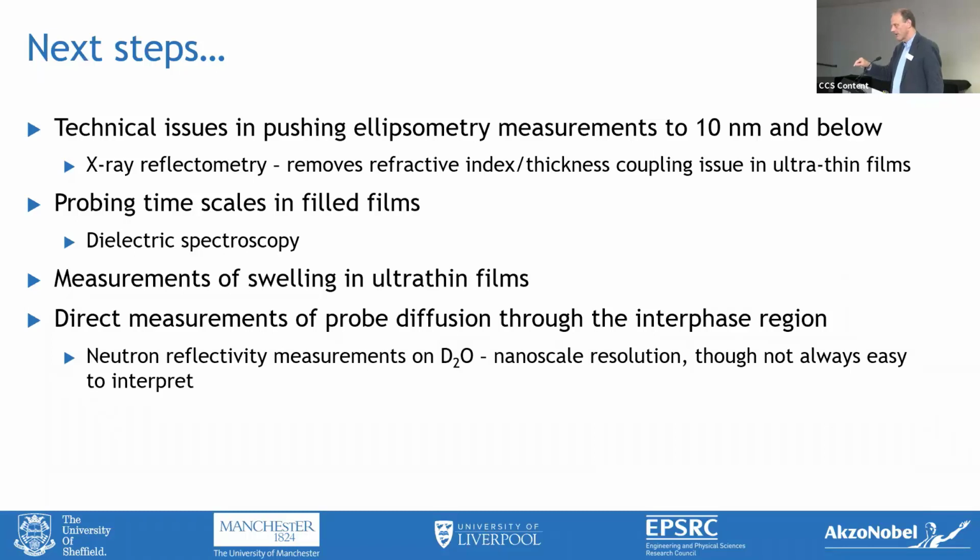It's just that the temperature dependence is less. As a first approximation, I would assume that as you reduce the temperature at high temperatures, you'll see an Arrhenius, exponential temperature dependence. As you go through the glass transition in the bulk, that Arrhenius dependence turns over into a Vogel-Fulcher temperature dependence, which is much, much stronger, really super exponential.